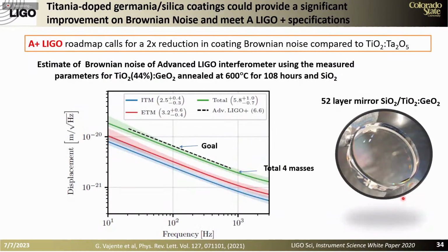So our colleague at Caltech, Gabriele Vajente, has done calculations that if we use 44% titania doped Germania annealed at 600 degrees for 108 hours, and we use this material in the design of a mirror with 52 layers, we can actually get a coating thermal noise that is of the same order as what is expected. I mean, it will have a reduction of a factor of 2 in coating Brownian noise, which is what LIGO expects for the coatings that will be used in the next upgrade of the interferometer.